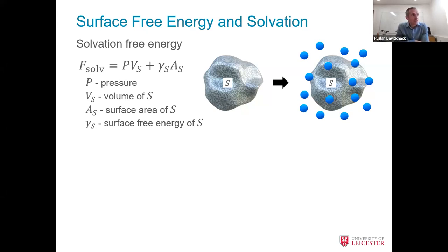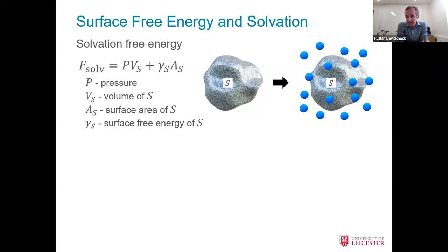When you do this, you need to work against the interaction between molecules in the solution — these blue particles. You have to create a sufficiently big cavity in that fluid. That work is pressure against volume, so the first term in solvation-free energy is the pressure of the fluid times the volume of particle S. The second term is related to the surface area of that particle — the work of rearranging the fluid to adopt the right configuration around that space.